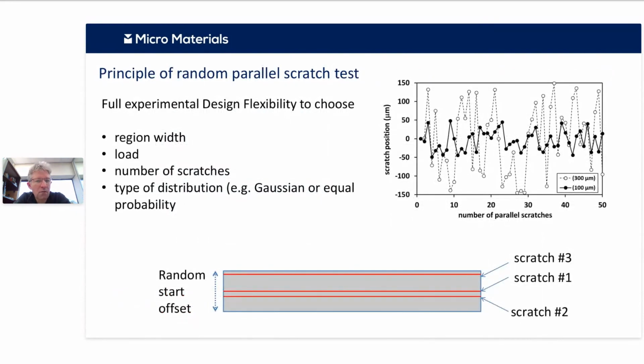And so what we've done with our nano scratch test is we've modified that or added some additional capability to allow us to produce these multi-pass scratch tests, where between each pass we move the position with a semi-random but computer-generated statistical distribution of start points. And these distributions can be normal around a surface position, or they can be so-called rectangular distributions where there's equal probability of starting anywhere. And we can change these region widths, and we can change the loads, and we can change the number of scratches.